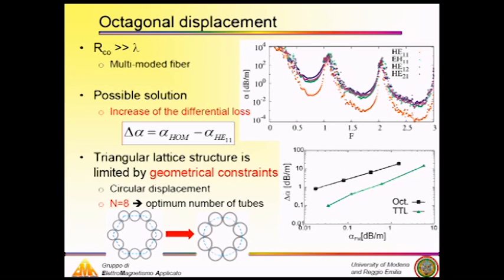We found also that the optimum number of tubes around the core, in order to increase the differential loss, is 8. As you can see from this graph, in which we plotted the differential loss with respect to the fundamental loss, moving from the triangular lattice structure to the octagonal one, we have an upshift of the curve, which means that at the same level of loss for the fundamental mode, we are increasing the differential loss. That is what we were looking for.